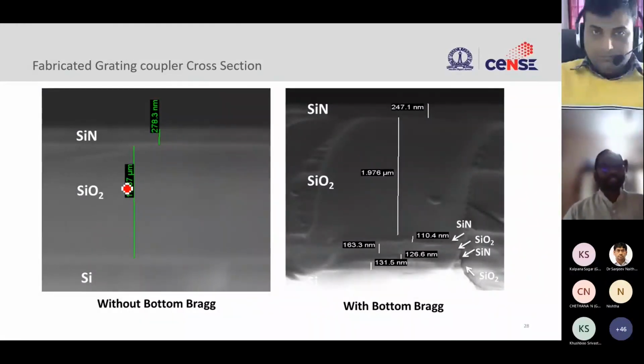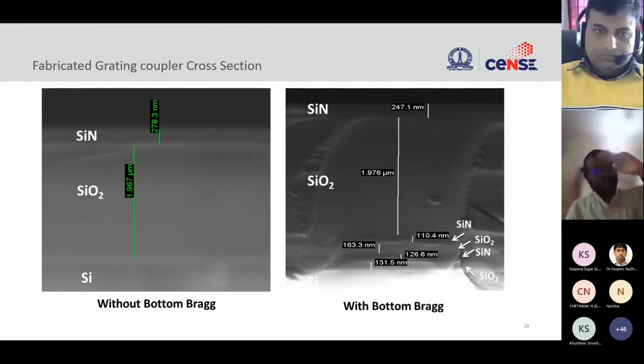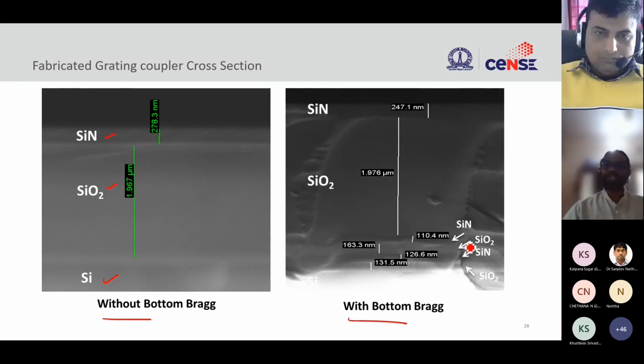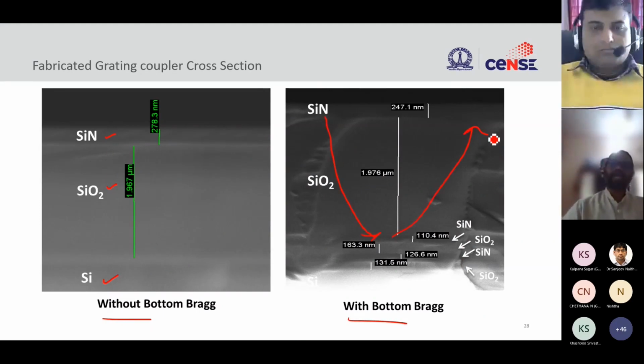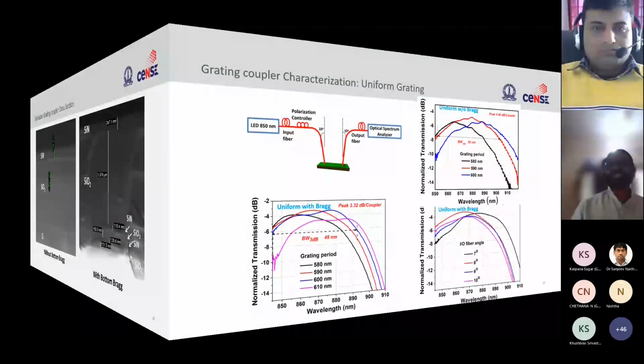And this is the cross section. You can see, you take this thin film and then you chop it, you cut it, and then look at the cross section like bread slices, right? You have this sandwich slice and then you look at what are all the ingredients. Like that we do it. You slice through it, and this is a scanning electron microscope image where we see silicon nitride, silicon dioxide, and silicon at the bottom. And with the mirrors, you can see the mirrors at the bottom. This is without mirror, and this is with the mirror. So you can see silicon and silicon dioxide where the light that will go in will be reflected back, all right? And this is the measurement for it.